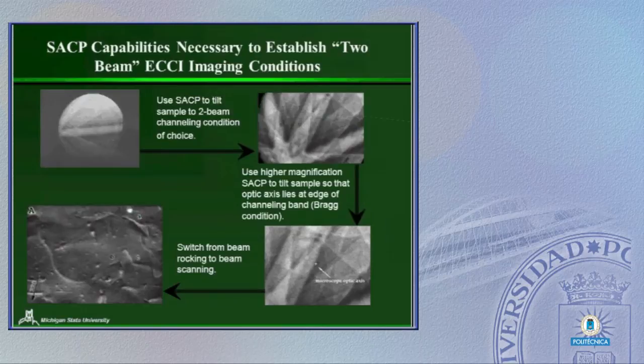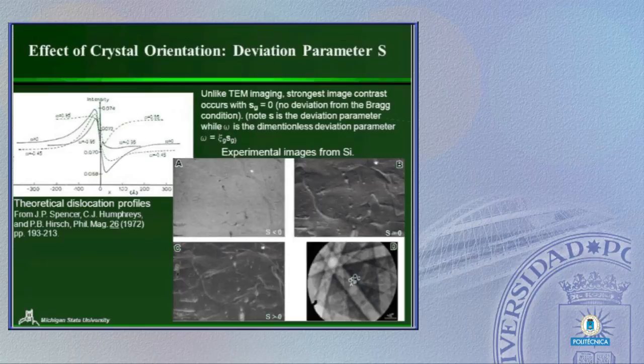Well, what we do here is we go to diffraction mode, we tilt to a 2-beam condition, we increase the magnification of that pattern, and we put the center of our pattern right on the edge of one of these channeling bands. And the reason we do that is this is where we get the most dramatic change in contrast between the dislocations bending the planes and the background. And then what we do is we just switch back to typical imaging mode. So here we're rocking the beam, and then here we're just rastering the beam back and forth across the sample. So in many ways, we can envision it a lot like what we do in diffraction contrast TEM.